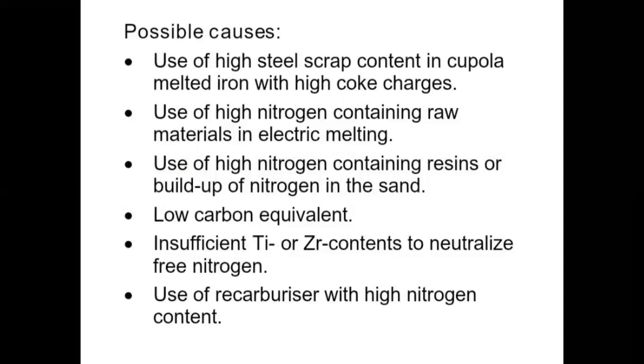Possible root causes: use of high steel scrap content in cupola melted iron with high coke charges; use of high nitrogen-containing raw materials in electric melting; use of high nitrogen-containing resins or built-up nitrogen in the sand; low carbon equivalent; insufficient titanium or zirconium content to neutralize free nitrogen; use of re-carburizer with high nitrogen content. These are the basic possible causes for nitrogen fissure.